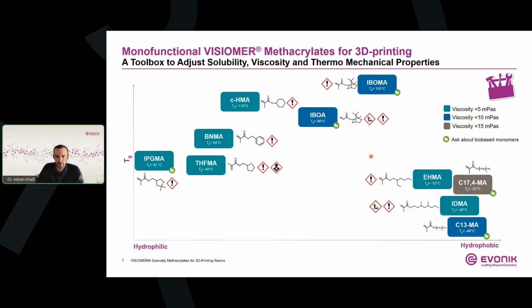For example, the VISIOMER portfolio contains a variety of long-chain alkyl methacrylates that can be used to adjust the hardness or softness of the final polymer. Typically, the longer the alkyl side chain, the lower the glass transition temperature of the final polymer, and the more flexible the resulting material. Here we also offer different types of alkyl or long-chain alkyl methacrylates that can differ in branching, like the EHMA and the IDMA,